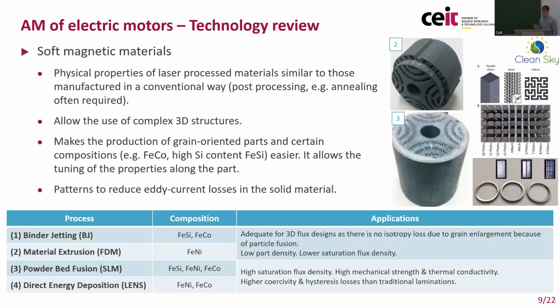The results are much more interesting for the soft magnetic materials, as Miren has explained. In this case, the material properties obtained, especially for powder bed fusion techniques, are quite good. Several examples of silicon iron, cobalt iron, or nickel iron materials can be found in the relevant literature.